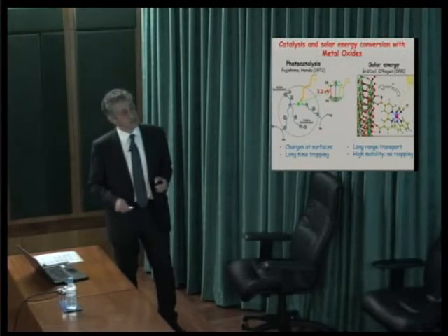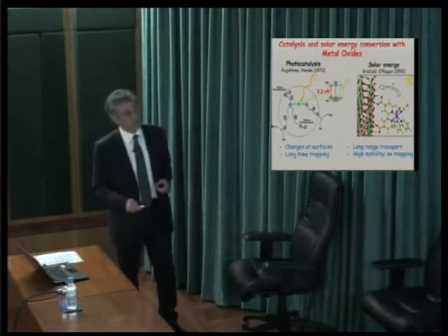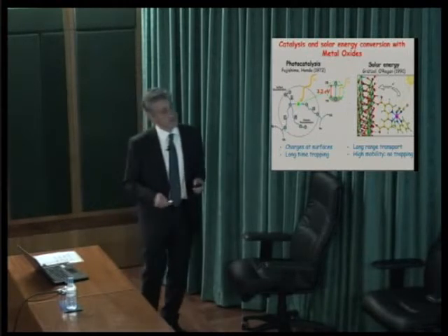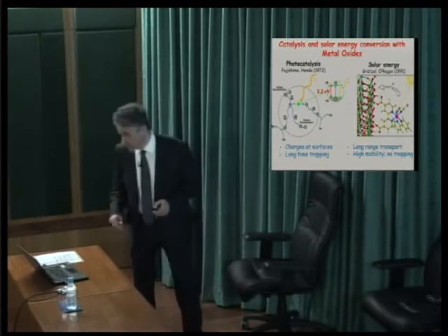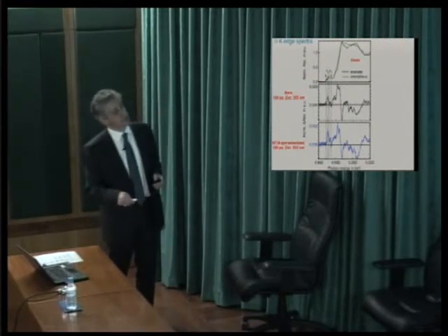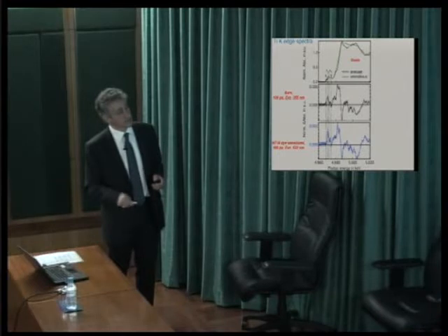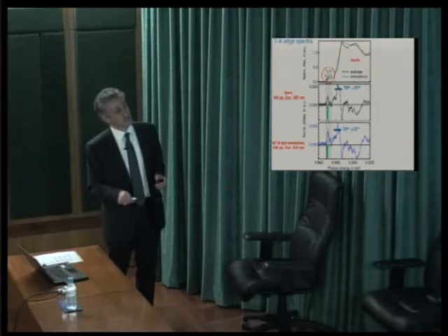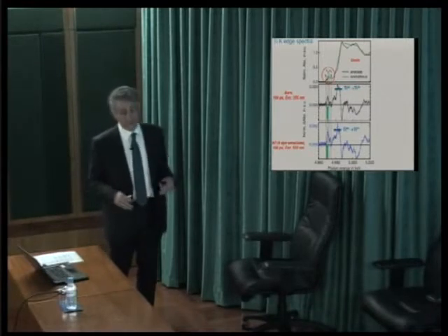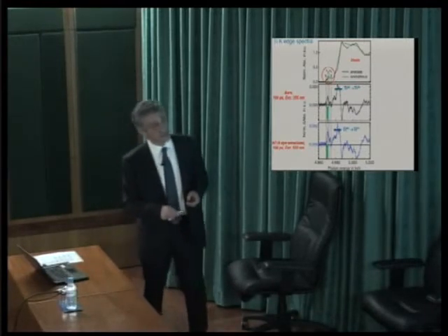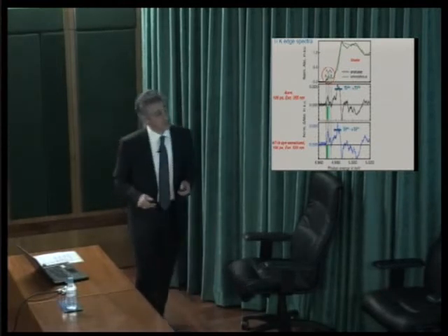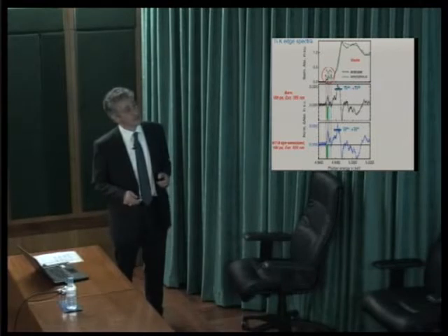So we did experiments with both bare and dye-sensitized titanium dioxide nanoparticles, where we probed the ruthenium atom in the sensitizer with X-rays and the titanium atoms also with X-rays in the substrate. And I don't want to spend too much time on this. These are the type of transients you get for the bare, for the dye-sensitized. Cut long story short, what we see is that the titanium atoms get reduced, that there is an enhancement of these bound-bound atomic transitions. So this is telling you something about changes in the symmetry, because these are d-d, formally forbidden transitions, but here they get enhanced, so you have a change in symmetry.